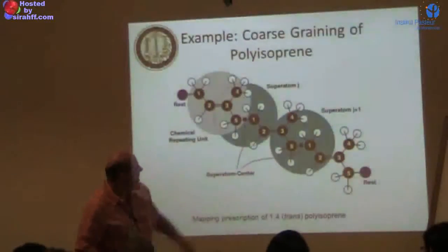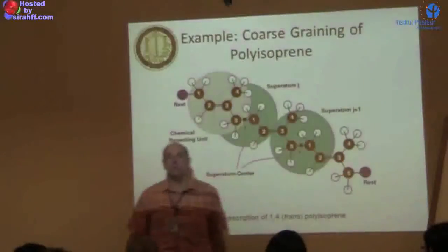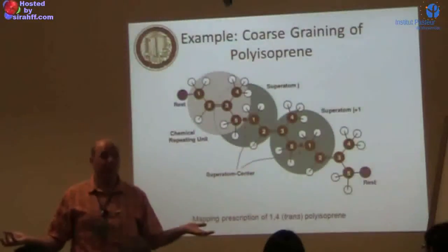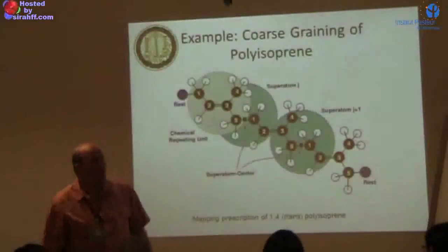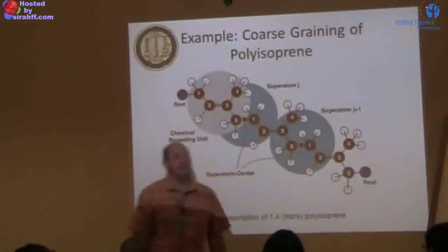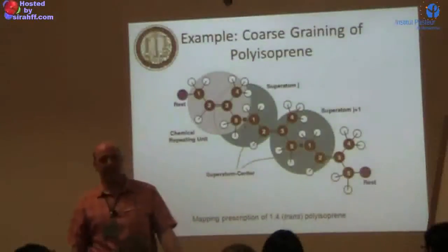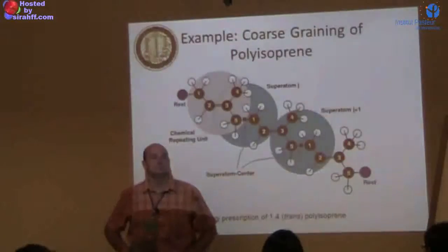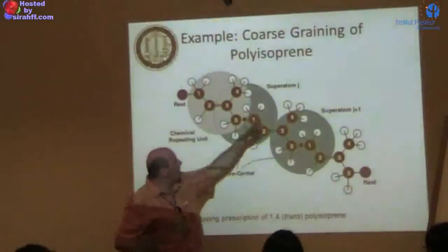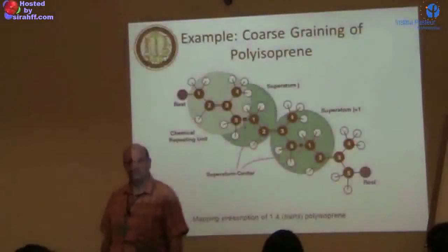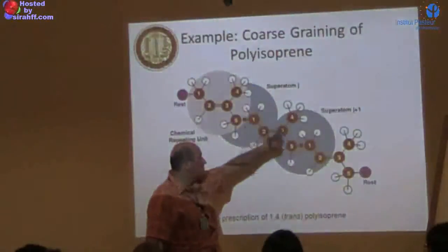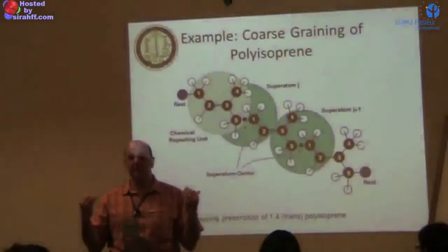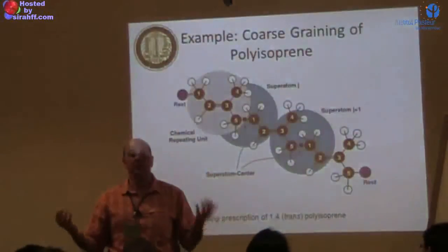On the other hand, if you're here, effectively you have largely this double bond. This double bond keeps everything down. This double bond cannot rotate. You would break a pi bond. So double bonds don't rotate, they wobble. This is defined. And in this polyisoprene, what does a double bond do in addition to not rotating? All these five atoms have an sp2 hybridization on C2 and on C3. The sp2 hybridization is then planar. So essentially, polyisoprene is a monomer of this. It's the real monomer.